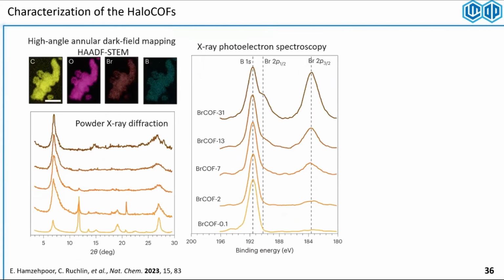Well, I went ahead with the synthesis. We made a series of different doping concentrations, looked at their crystallinity, making sure the phase is still observed. The amount of dopant could be easily identified by the high resolution XPS as well, because boron orbitals and halogen orbitals look surprisingly close in the XPS, and we looked at homogeneity of the halogens inside these particles, just to make sure we don't have a chunk of highly doped COF and a chunk of non-doped COF.